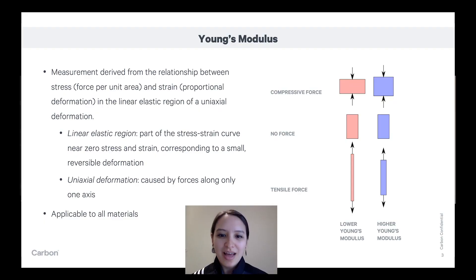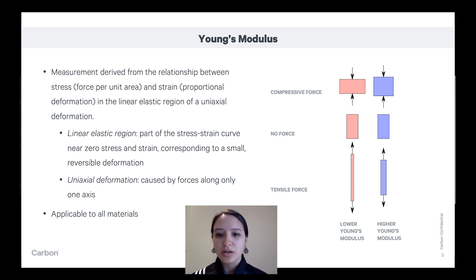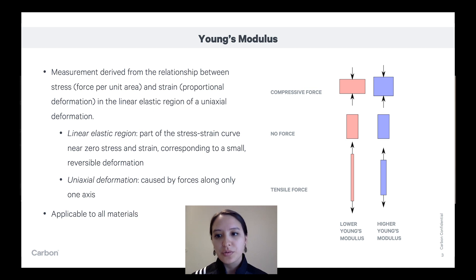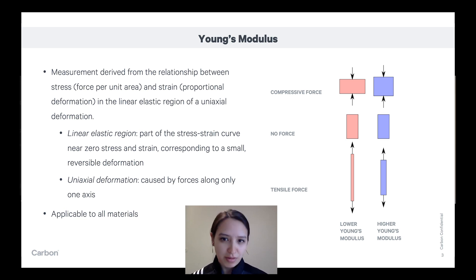The linear elastic region is the part of the stress-strain curve that's really near zero stress and strain — right when you're just beginning to deform a material — and it has to correspond to a small, reversible deformation. For Young's modulus, it's really critical that it is reversible, because if you look at deformations beyond that, you can be getting into areas where you can't really compare things anymore.